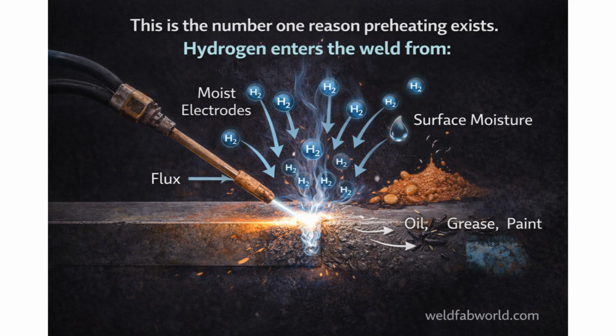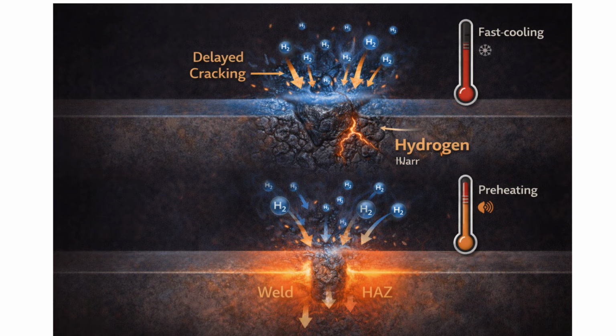Metallurgical reasons for preheating. Now let's talk metallurgy, but don't worry, I'll keep it simple and practical. Hydrogen-induced cracking. This is the number one reason preheating exists. Hydrogen enters the weld from moist electrodes, flux surface moisture, oil, grease, paint. When welding happens, hydrogen dissolves into molten weld metal. That part is unavoidable. The problem starts after welding. If the weld cools too fast, hydrogen gets trapped inside hard microstructures and creates pressure. That pressure leads to delayed cracking, sometimes hours or even days later. Preheating helps by allowing hydrogen to escape slowly, reducing hydrogen concentration in the weld.